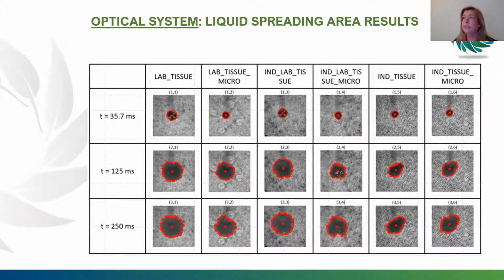The evolution of the liquid droplet spreading over time in samples with and without embossing is presented in this image. The sample complexity goes from the left to the right. The first column is for an isotropic 100% eucalyptus paper, and the second is for the same paper structure embossed with the micro pattern. The middle columns of the image are for the paper structure obtained after disintegration of the industrial-based paper. These are isotropic structures with the same mixture of hardwood and softwood of the industrial-based paper without the creping effect. The third column is without embossing and the fourth with embossing.